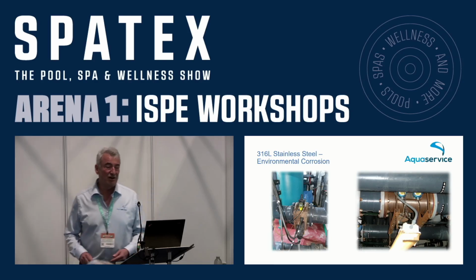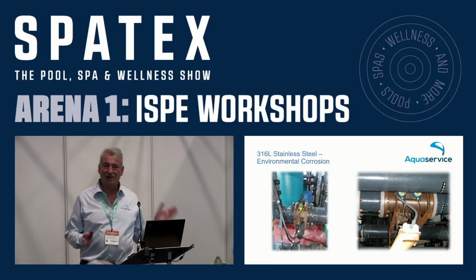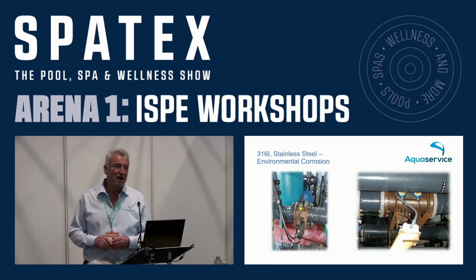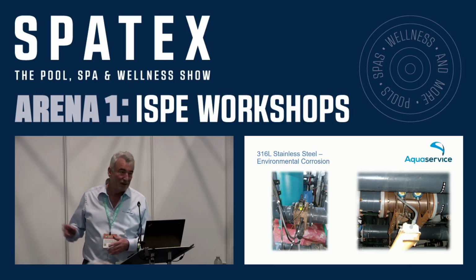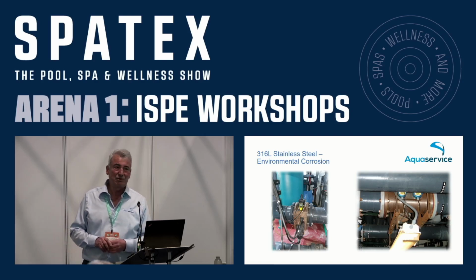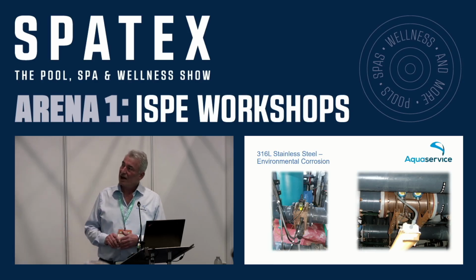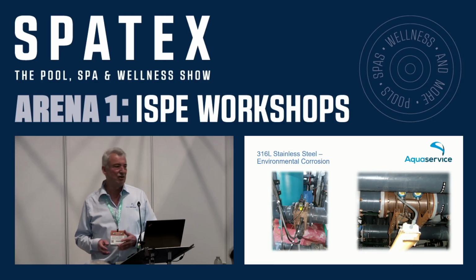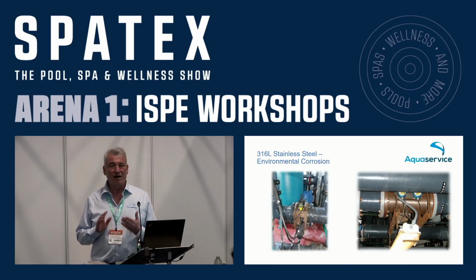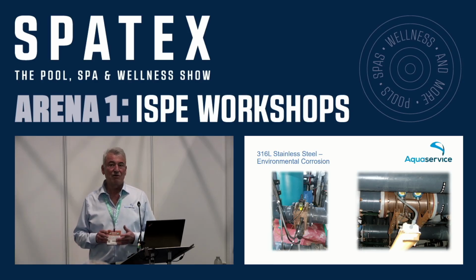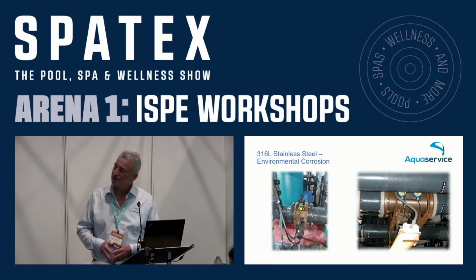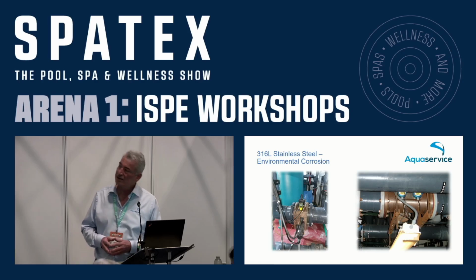And the images I show here, now there are various types of corrosion that can occur in a swimming pool plant room. I'm calling this environmental corrosion. So these are two UV chambers. The one on the left is installed outside Rome in Italy, and that photograph was taken 14 months after it was installed. So quite clearly, it didn't leave the factory in that condition. It's probably corrosion due to atmospheric conditions, high humidity, high temperature, and more than likely some chemical releases from mixing perhaps hypo and acid.